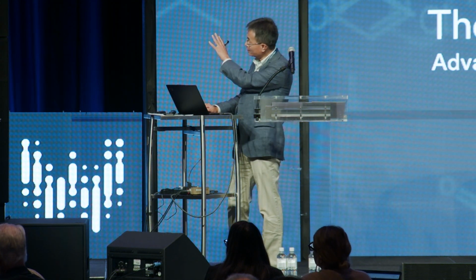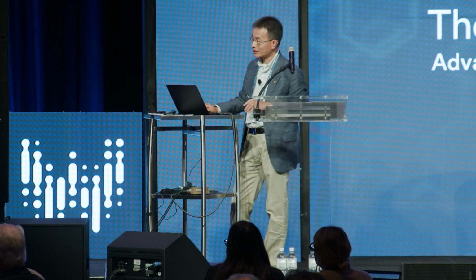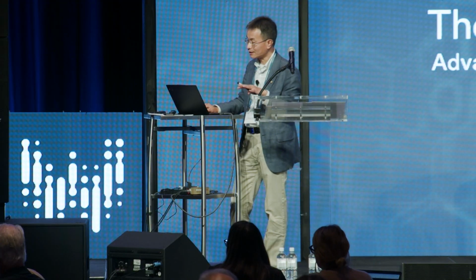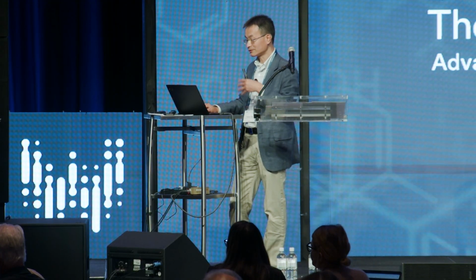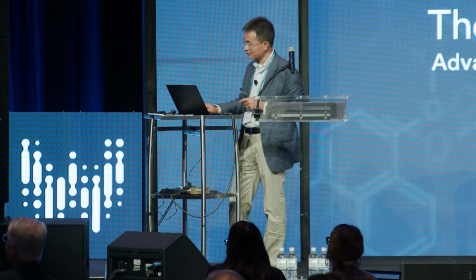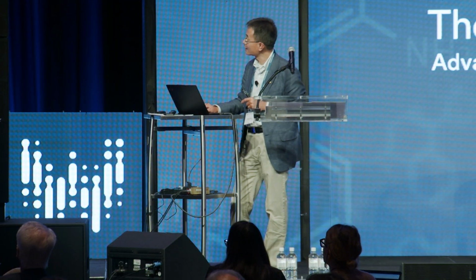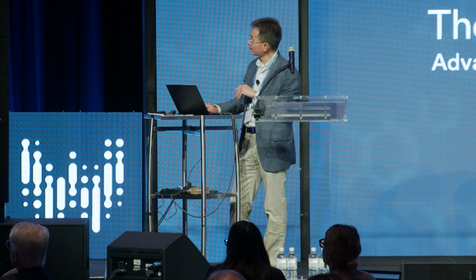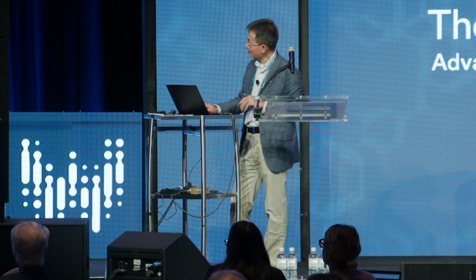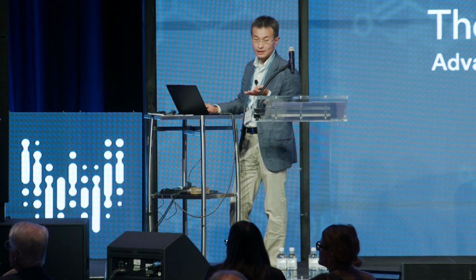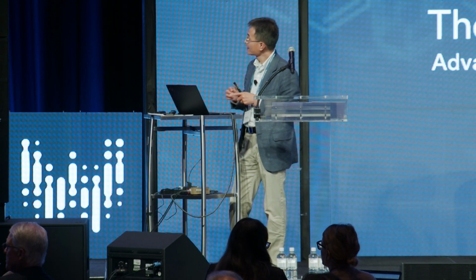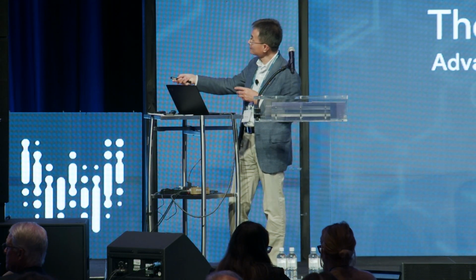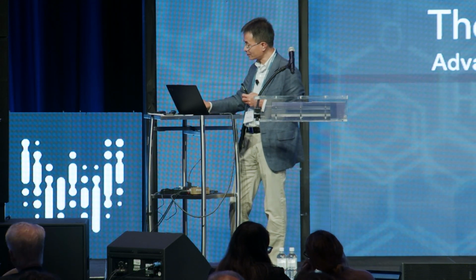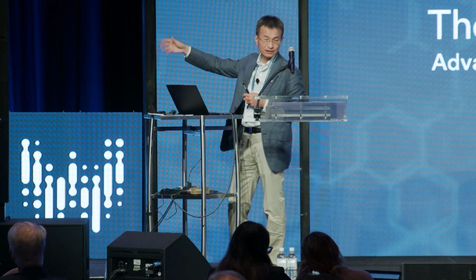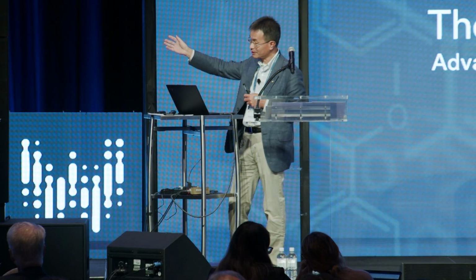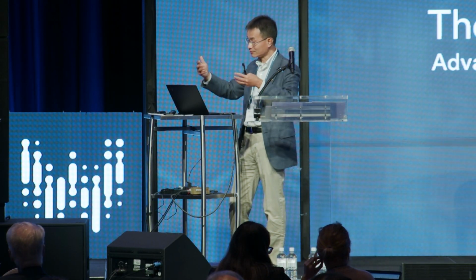And these are the typical photocathodes. They have light trapping phenomena: light goes in and cannot escape until it is absorbed. That's the unique feature of these high-density nanowire arrays. They have very high surface area, and you can decorate them with all sorts of different catalysts you can develop in your lab. And notice the photocurrent density. I think in Michael's talk this morning, in one-sun condition, you can easily generate 20, 30 milliamps per square centimeter in terms of the electron flux you can use to do chemistry.